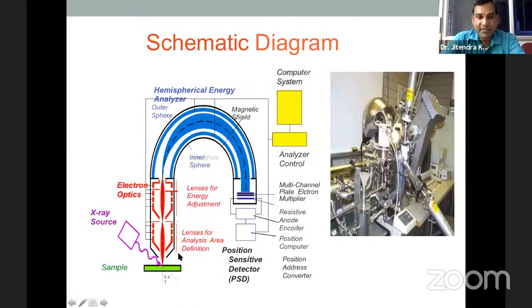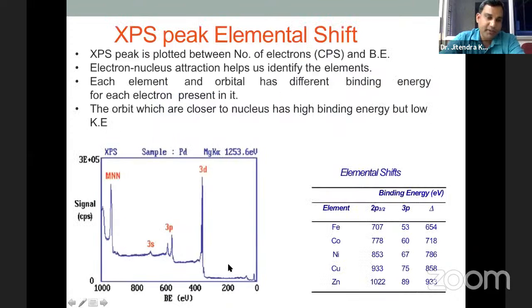So this is the basic setup of your XPS, and we use very complicated sensors here. We apply the samples, and then the electron beam and X-ray sources, and the Auger electrons are captured by the detector. Each material has a different wavelength, and according to that we capture it in peak form. So this is a kind of peak. You can generate the signals at that particular electron volt energy, and in this way you can analyze what type of element is present in that particular component. According to the wavelength and concentration, we check that element.